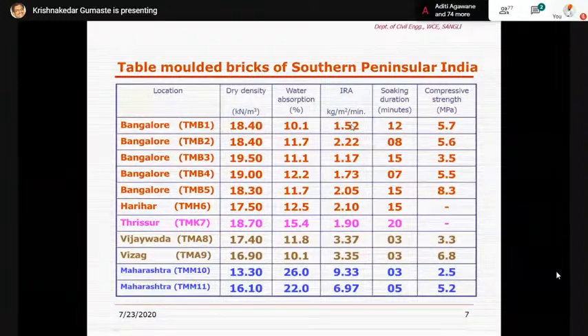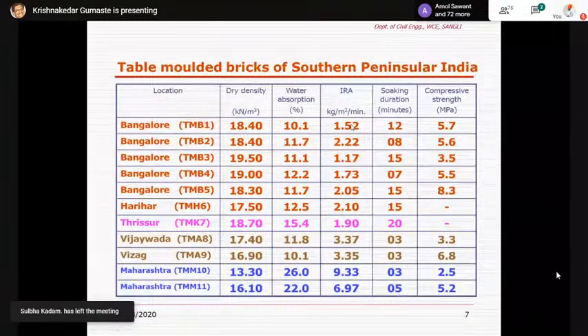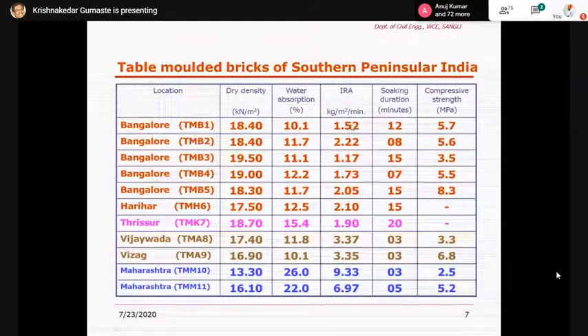IRA seems to be an important property, and IRA, initial rate of absorption, can be defined as the amount of water that is absorbed by the base of the brick when subjected to a 3 mm pool of water for a period of 1 minute. So it is a very simple test that can be performed on the sites, where a brick can be placed in a small 3 mm pool of water for a period of 1 minute. And you can see what was the dry weight and the weight of water that has been absorbed in the duration of 1 minute. That absorption is expressed as the amount of water in kgs per meter square, that is the bed surface of the brick, for 1 minute duration.